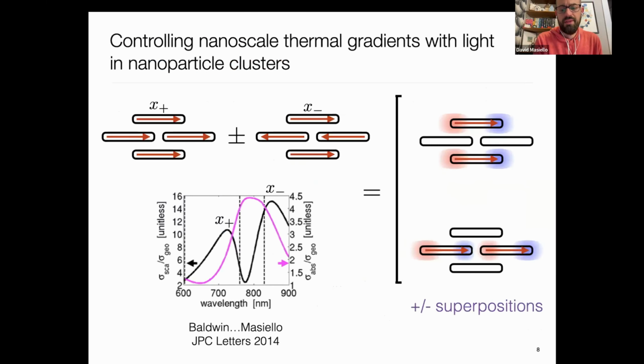So this story begins back in 2014, where together with a graduate student, Chris Baldwin, we started to play around with a plasmonic nanorod system with four nanorods. The outer two are on the order of 200 nanometers in length, and the inner two are on the order of 250 nanometers in length. I don't remember the numbers exactly, but they're slightly different.